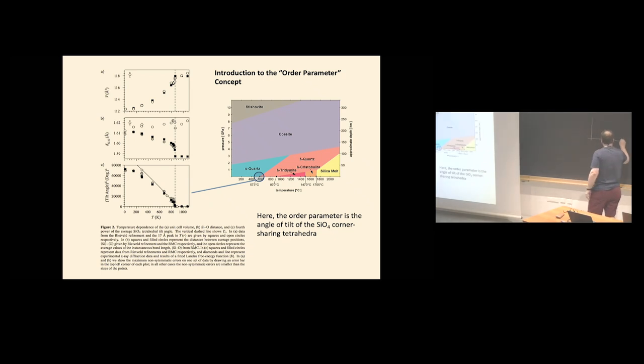Yeah, so normally I think, and I'm going to draw these in a minute, you would expect to see the order parameter here, and you'd have TC here, and it would come down 0, 0, 0, 0, 0, and then something would happen at this point and it'd be a curve, right? So it would curve up like this. And quite often that curve, you can get Q squared proportional to TC minus T, or you can get Q to the fourth proportional to TC minus T. And those would be two very classical results.